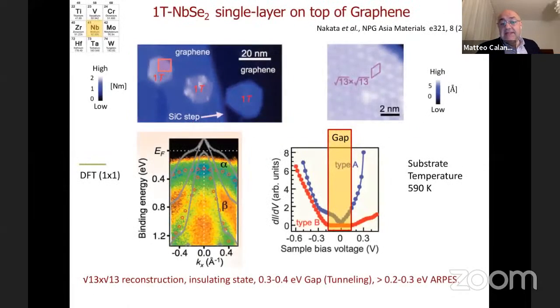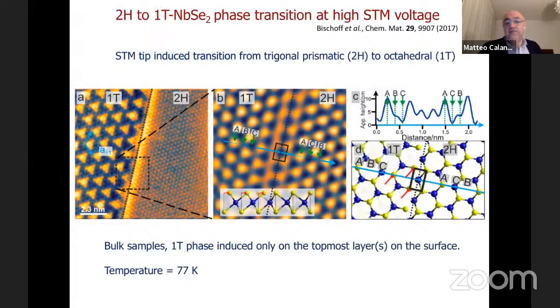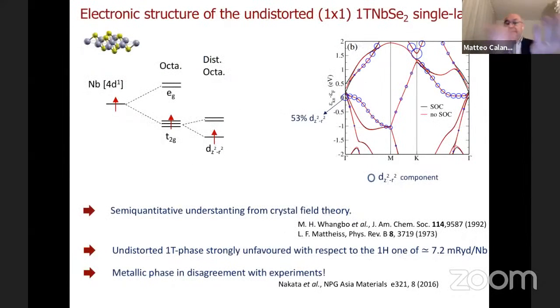I will not tell you the full story, but these systems are very analogous to tantalum disulfide because they undergo a square root of 13 reconstruction, the Star of David, which you probably know very well. The electronic structure of the undistorted structure has one electron in the dz² orbital, and when you have the square root of 13 times square root of 13 reconstruction, you have an unpaired electron left because you have 13 atoms. So if this is an insulator, it cannot be a band insulator because you have an unpaired electron, unless it is magnetic.